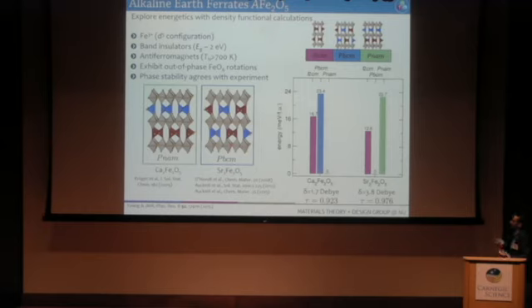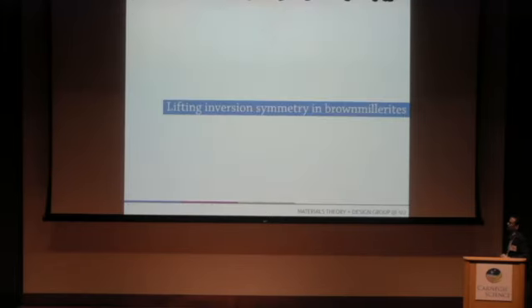Okay? If you look at the energy scales, you should anticipate that there can be some mixture in a real sample, and this indeed has been observed. And for a long time, it gave quite a bit of confusion to the experimental community about what the real or equilibrium structures are of these two different materials. And so calcium has a smaller tolerance factor. Calcium is just smaller, so you have larger rotations in the structure, just like in perovskite.